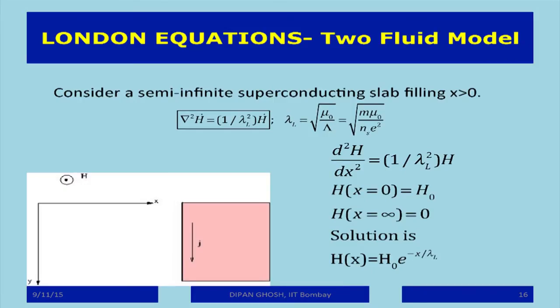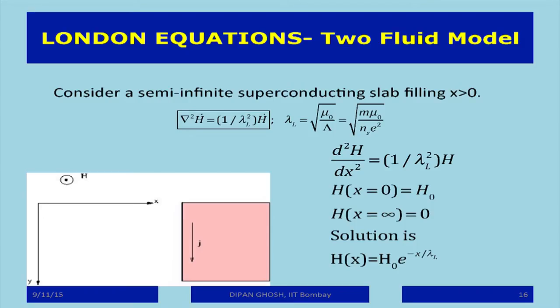All right. So I've got an equation. Now let me give you an example of how this equation helps us in understanding the Meissner effect. So notice this, that the equation that I gave you was this, del square H equal to 1 over lambda square H. The geometry that I have given here is the following: consider a superconducting material which occupies the entire semi-infinite region x greater than 0. In other words, x equal to 0 is its boundary surface, and it extends all the way to infinity. And then I have applied a magnetic field in the z direction. This is the geometry. The cross section of this slab is perpendicular to the plane of the blackboard. The magnetic field is in the outward direction.